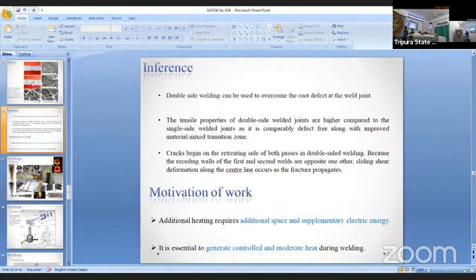So we can conclude from here that double-sided welding can be used to overcome the root defects of the weld joint, which were seen using the conventional friction stir tool. And the tensile properties of double-sided welded joints are higher compared to the single-sided welded joints, as I've already mentioned. It is comparatively defect-free.